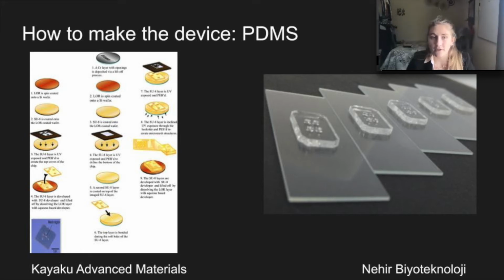Photolithography is a very complicated and detailed process, and the petri dish is filled with a mixture of PDMS and curing agent in a 10-to-1 ratio. The PDMS and curing agent is weighed out, and usually to fill a petri dish for the first time, it is around 70 grams of PDMS. The petri dish is then placed in a vacuum chamber to suck all of the air bubbles out of the PDMS for about 20 minutes. Once the air bubbles are out of the PDMS, it can be left to set. It can be set at room temperature, and that takes about 4 days, or it can be placed in the hot oven at about 100 degrees Celsius if it is in a glass petri dish.